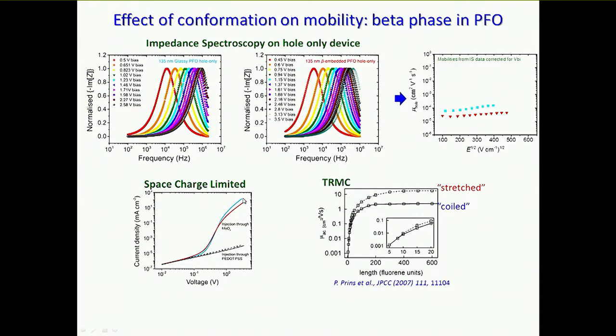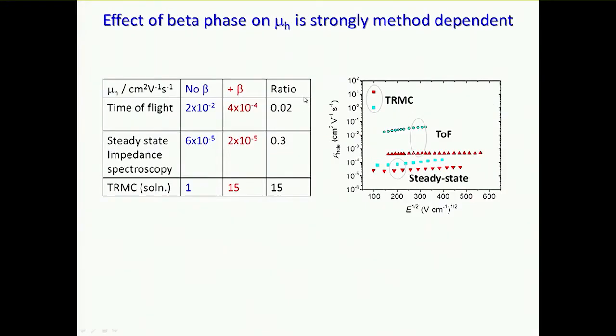And then finally, we looked at the literature where measurements had been done using a technique called transient microwave conductivity, and they could probe the in-chain mobility effectively within a single chain or maybe within a conjugated segment. And in that case, they find that when they stretch the chain, which is like preparing it in the beta phase, the mobility is actually higher. So we put everything together, and we find, okay, 3 different measurement techniques.